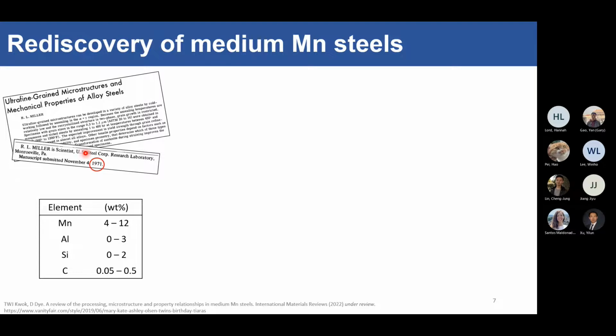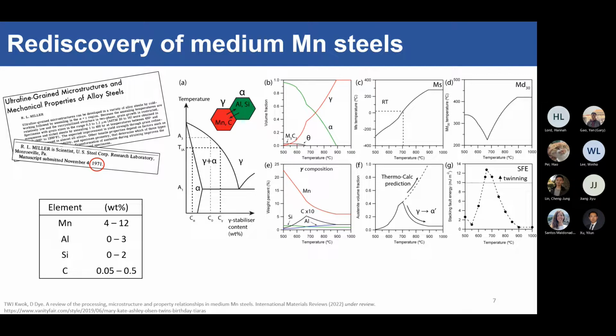But modern medium manganese steels now have 4 to 12 weight% manganese. So this is a big improvement, or rather big reduction of manganese content compared to your TWIP steels, which was 16 to 30. So we are way, way, way lower levels right now. And the key to medium manganese steels is this thing called element partitioning. Because we've reduced the amount of austenite stabilizers, now your microstructure is both austenite and ferrite at the same time. It cannot be fully austenitic anymore.